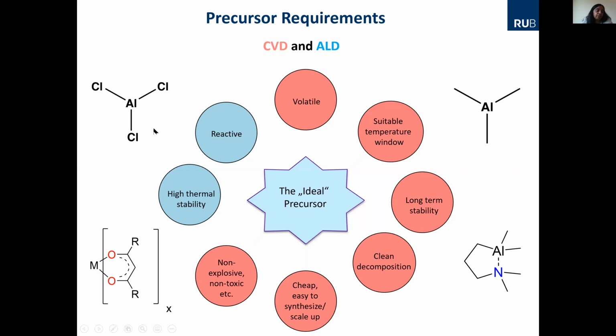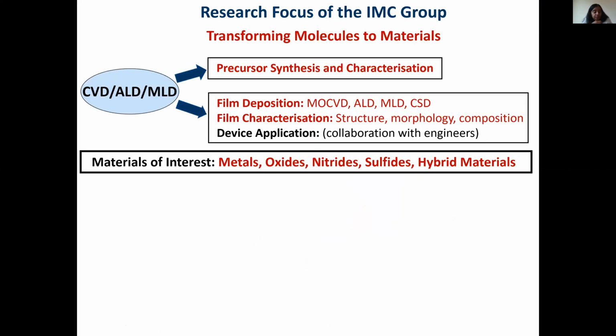So the role of a chemist is to develop new molecules, go away from the classical precursors because there are certain drawbacks with them. And we researchers look into such details, where we can think of having different ligands, combinations of ligands, be it nitrogen coordinated, oxygen coordinated, or just halogen coordinated ligands, and see if we can improve upon the existing class of precursors. So my research group's main focus is transforming molecules to materials. So we look at inorganic molecules, organic molecules, and transform them to materials using CVD or ALD.